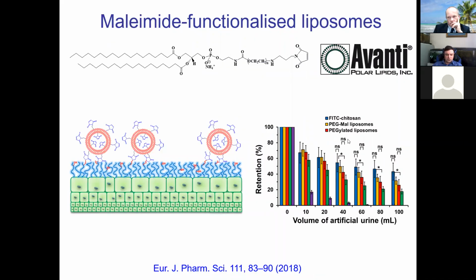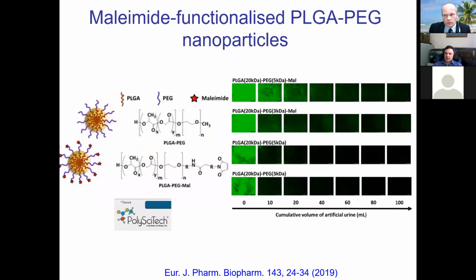Later, when I delivered one of my talks at pharmaceutical conferences, I had interest from several pharmaceutical scientists, and they complained that, oh, your synthesis with maleimides is too complex. Can you do something simpler? Then I started looking around, and apparently I found some commercial products already available with maleimide groups, phospholipids functionalized with maleimides. We designed liposomes functionalized with maleimides, and also demonstrated that these liposomes are much stickier to mucosa compared to their control samples without maleimide groups.